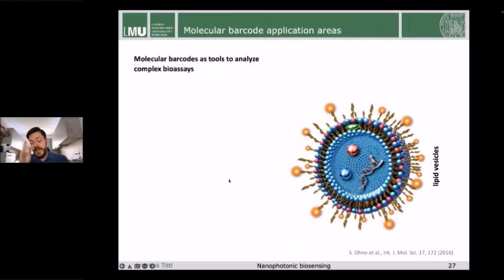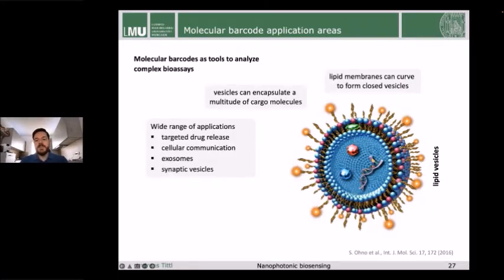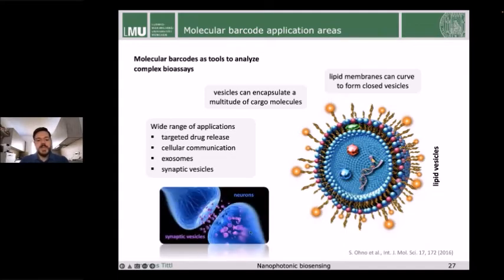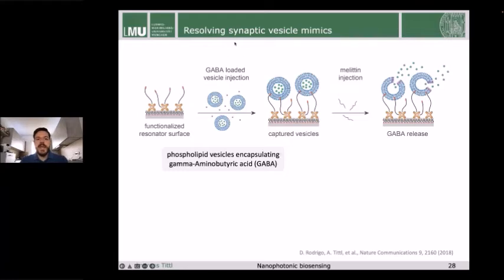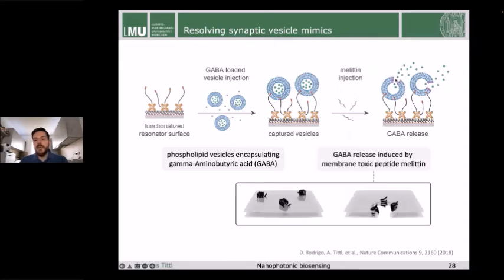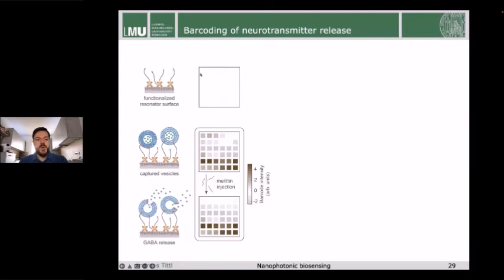So I just briefly want to show you that this can also be applied to more complex biological systems. To do that, we looked at so-called lipid vesicles, which are important in the body as molecular shuttles for targeted drug release or cellular communication. Specifically, we looked at synaptic vesicles, which are used to transfer information between neurons in the brain. We made some mimics of synaptic vesicles by placing a neurotransmitter inside these vesicles and attaching them to our sensor metasurface, and then perforating these vesicles using a membrane toxic peptide, melittin. And we could show that with our barcoding method, we can quite nicely track both the attachment of the vesicles and the release of the GABA.